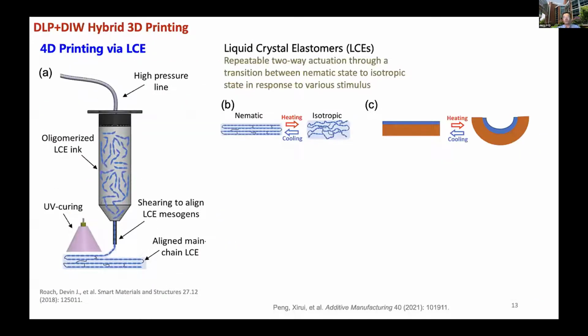And also, liquid crystal elastomer is one of the well-known active materials that's been used for 4D printing. The advantage of liquid crystal elastomer is that the shape change is reversible. So as you heat it up, the polymer LC will shrink, and as you cool it down, it will expand. Typically, it is because you have this kind of molecular arrangement. We call them mesogens, which are liquid crystals, right? So if you align them after your fabrication with LCE, at room temperature, they are aligned. And as you heat it up, due to the increase of temperature, the alignment actually is lost, and they become isotropic. So this is causing the shrinkage.